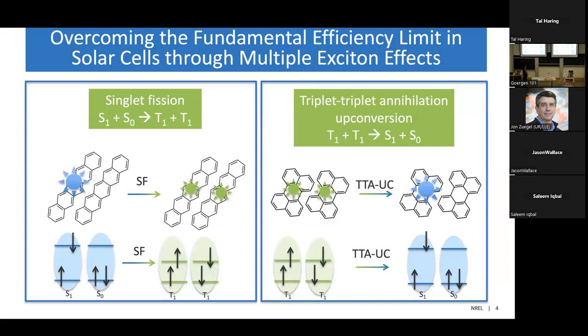So in the case of singlet fission, after photoexciting one of these pentacene molecules, that energy can then be divided between two lower energy triplets now residing on neighboring pentacene molecules. And then triplet-triplet annihilation upconversion is the opposite process, where you start with two triplet excitons, and they can actually pool their energy together to create one high energy singlet, and then the other perylene molecule relaxes to its ground state.